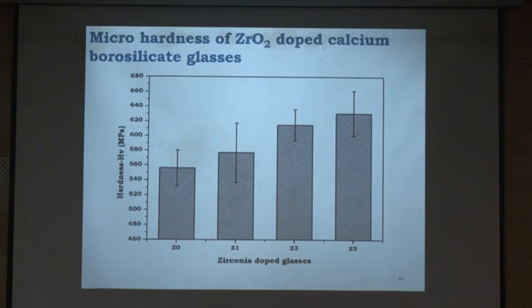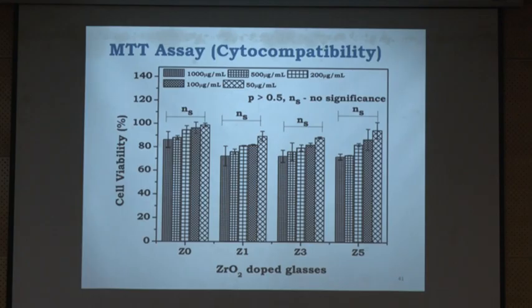And similarly, we have measured the mechanical properties also. So zirconium is about 600 to 620 range we are getting. I am talking about the hardness, which is very good as far as the mechanical properties are concerned. A hardness of 600 is not a small thing, right? So we are able to use it for hard tissues. That is the advantage. And this is to confirm whether the material is toxic or not.